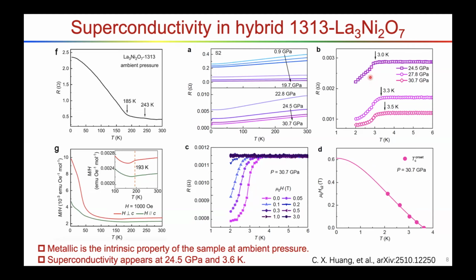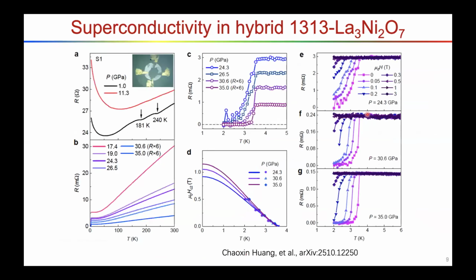But as you can see here, there's only a small drop in the resistance. Okay, so we repeated the measurements on another piece of single crystal. Okay, so here is the measurement at a low temperature, a low pressure. We see some anomalies in resistance, and as you can see here, we see perfect zero resistance. Okay, the transition temperature is at 3.6 Kelvin. When we apply a magnetic field, the superconductivity is suppressed. The upper critical field is at 1 Tesla. Okay, so that means it is indeed a real superconducting transition, but the transition temperature is quite low.